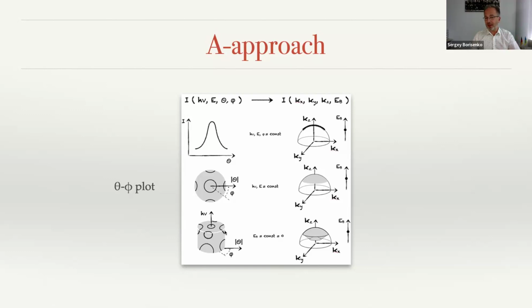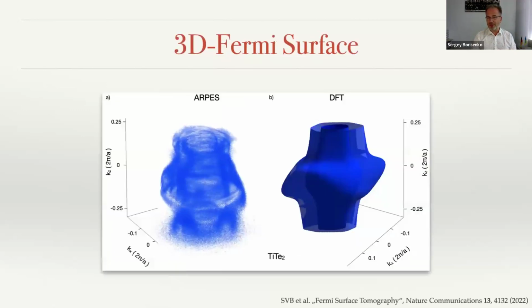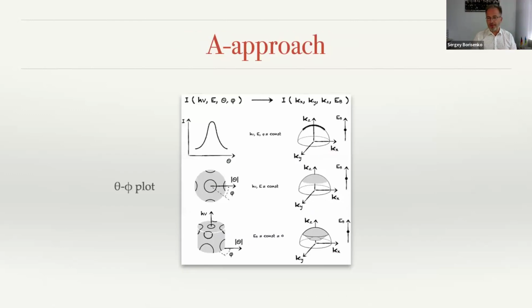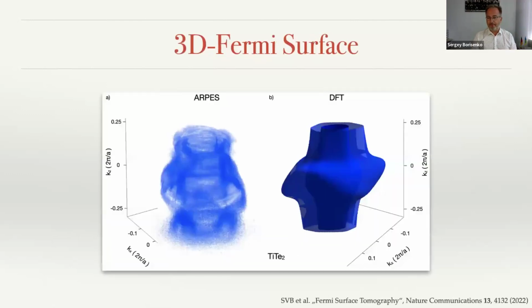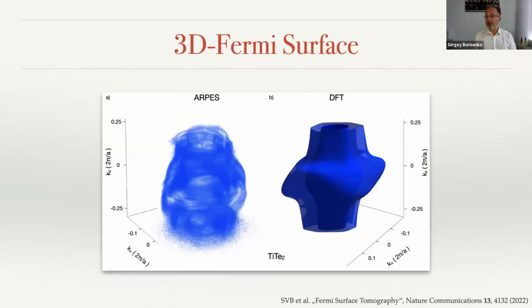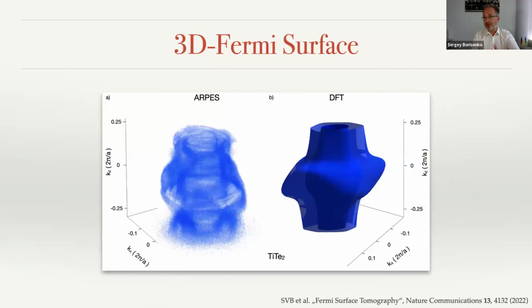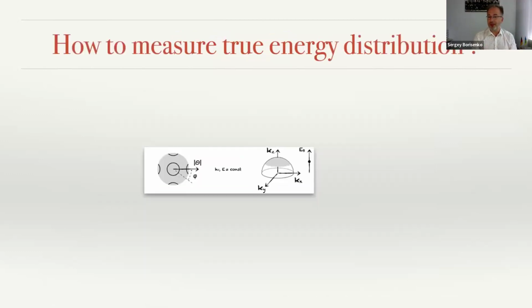Finally, if one scans other angles, one arrives at the 3-dimensional plot, which is measured in the spherical sector. So one can measure 3-dimensional Fermi surfaces with the A approach. If one concentrates on angles, this is transparent physical meaning, so you can measure 3-dimensional Fermi surfaces and compare directly with DFT. How to measure true energy distribution?